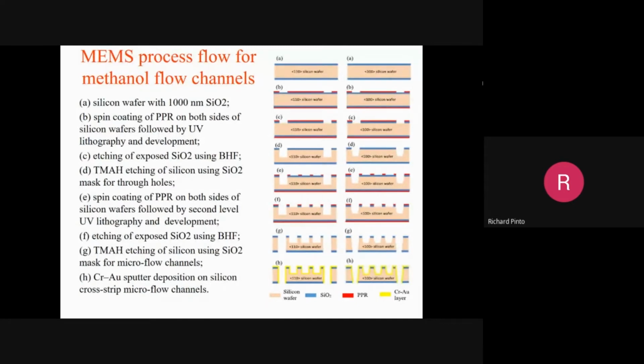While etching through silicon, we use 2-inch diameter silicon, which is about 360 micron thick. You go halfway through, something like 180, 200 micron, using TMAH. Then again strip the resist, spin oxide, and spin coat positive resist on both sides of the silicon wafer, followed by second level UV lithography and development. Etching of exposed silicon dioxide using BHF, then TMAH etching of silicon, G, using the silicon dioxide mask for micro channels. The first mask is for through holes.